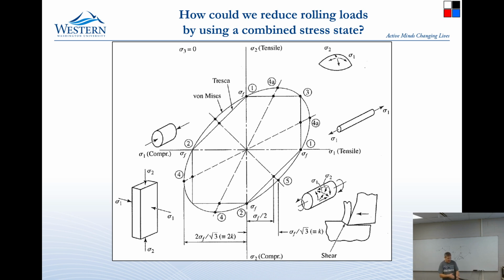But what actually happens is as I am squashing, the material both wants to get longer, but it would like to get wider as well. And the friction along the roll prevents it from getting wider. So it actually happens at this 1.15 times sigma F. And the fact that it can't get wider leads to some really interesting things that happen when you are rolling.